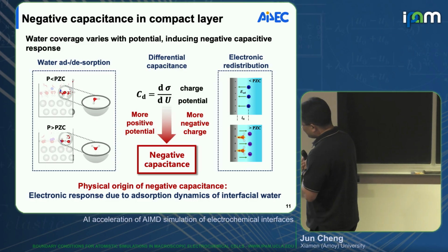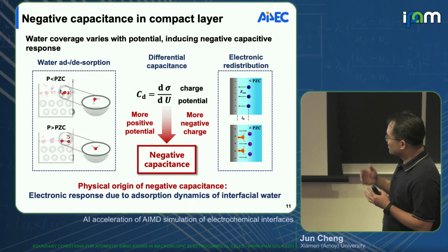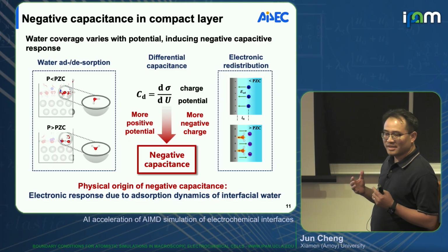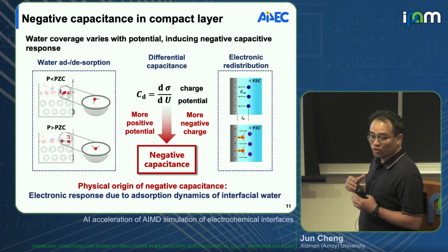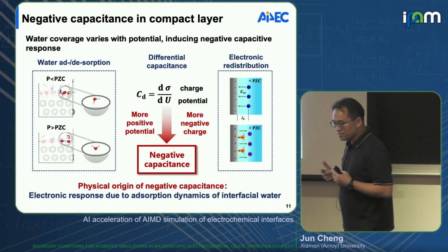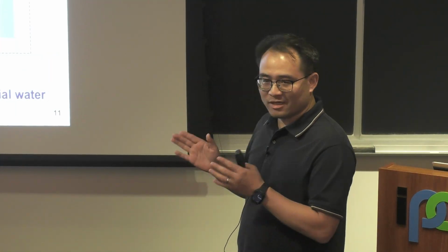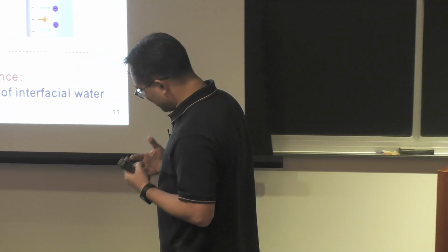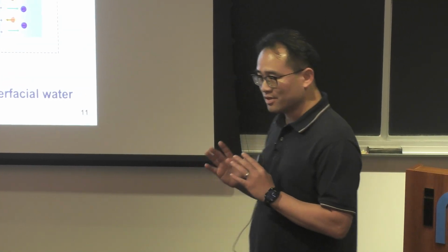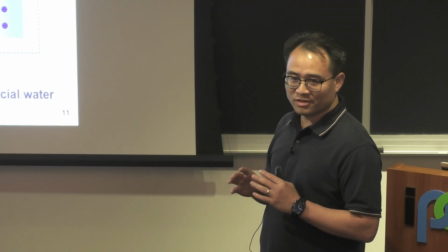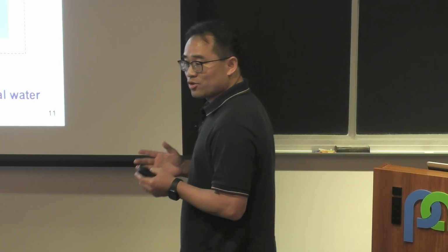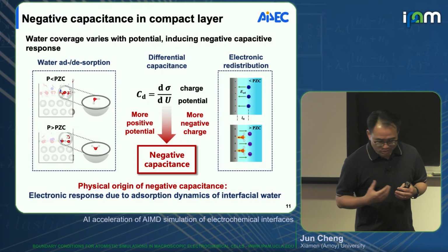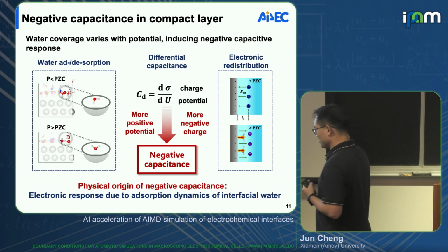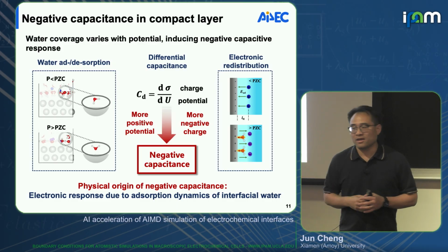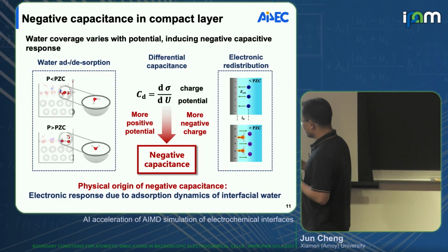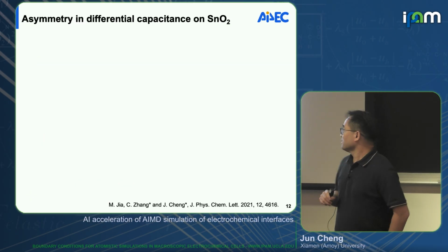Okay, just to point out, this negative capacitance, if you think about its physical origin, it's due to the electronic response, okay? Due to adsorption dynamics, the interface water. Think of the community, there are two groups of thinking, right? One is we want to treat the electrostatics of the electrode double layer. Many people in the field apply classical molecular dynamics where you don't treat electronic structure. Even if you have a polarizable force field for the electrode, it is still missing the chemisorption part. And of course, for the DFT community, where we want to look at electrocatalysis, for instance, we do not explicitly treat the molecular dynamics of the electrolyte solution, so you will miss out this effect. So ab initio molecular dynamics is really key in treating this system.